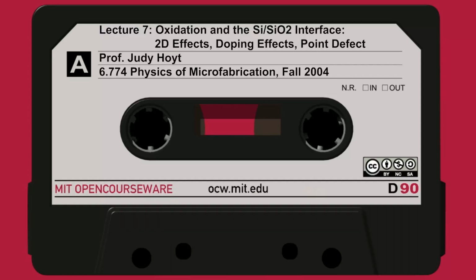So let's just say on slide 34 that these extra vacancies are available to provide sites for the oxidation reaction. Then we can imagine writing B over A equal to some number, R1, where R1 has to do with all the mechanisms other than vacancy-driven processes. Obviously, oxidation is not only controlled by vacancies, it's controlled by a lot of things. But there must be some term added in, this K times C_V total.